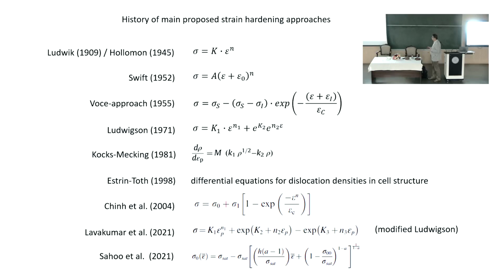It's increasing and also decreasing - there is production of new dislocations, there is annihilation of old ones. And with this small number of parameters, you still have to go up from the microscopic level to the macroscopic one, using the Taylor factor, the Taylor equation, which directly relates the dislocation density to the strength of the material.